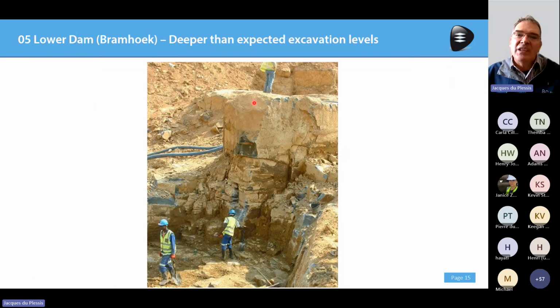Now, just imagine yourself seeing the core log for a core that was drilled into this material. I think you can agree that once you get there, you would think you're on pretty solid rock, and you only have to excavate up to that level. But what we discovered on site was these huge boulders, just actually loose rock blocks, standing on top of each other with clay seams in between. And those clay seams also made the grouting difficult because you couldn't get the grout to go in there. So we struggled to seal all the joints.